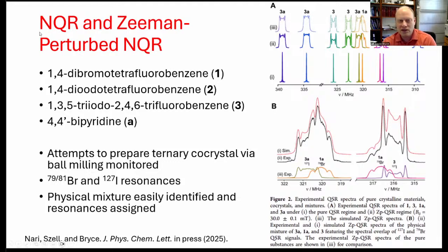But using this NQR and Zeeman perturbed NQR approach, we're actually able to get quite good spectra that we can interpret for these very difficult NMR nuclei like iodine and bromine. So what I'm showing at the top here is nuclear quadrupole resonance spectra of mechanochemically formed cocrystal 3A. Nice sharp peak. There's actually 2 peaks. Same for pure compound 3, 1A, and 1. Okay, so all very well resolved, very easy to do, despite the fact that these are difficult nuclei. Again, no purification needed. You can take it right from the ball mill or whatever.